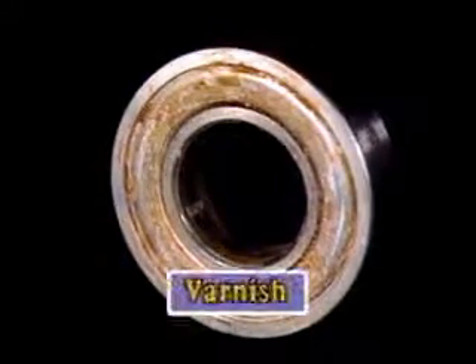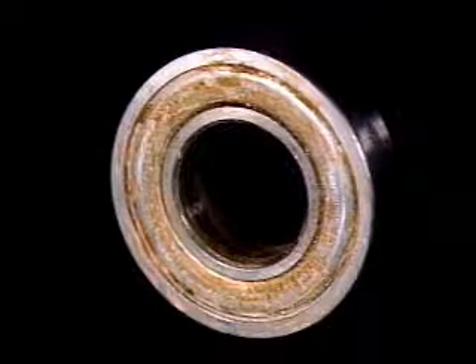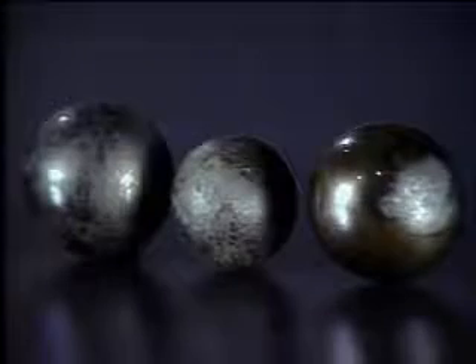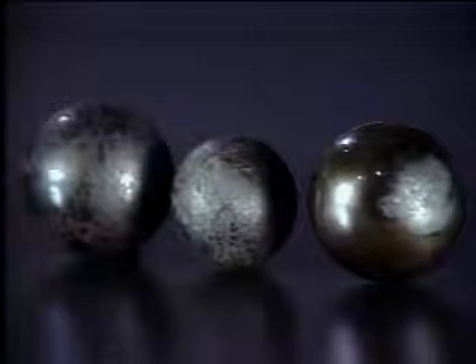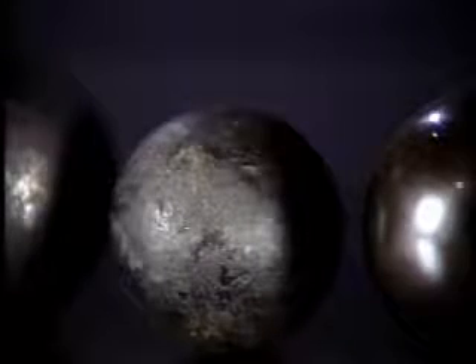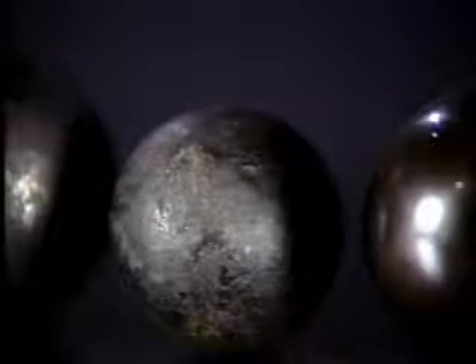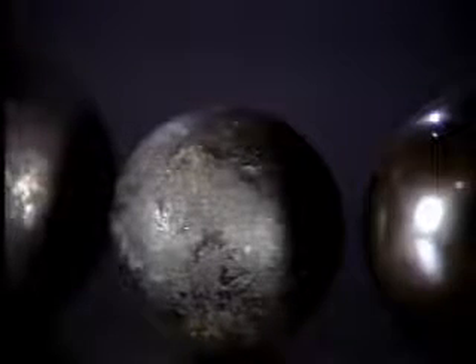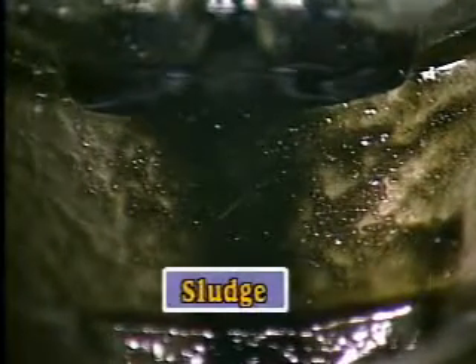Besides forming acids, lubricant oxidation can form harmful deposits on metal surfaces. The varnish deposits on this bearing came from oxidized grease. More severe oxidation produces carbon deposits. Both varnish and carbon deposits can greatly increase friction on bearings and other machine parts and keep them from operating freely. Carbon deposits can also collect in lubricants and form sludge. Sludge can clog lubricant pathways in machinery and keep the lubricant from getting to where it's needed.